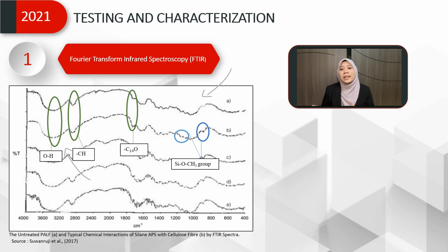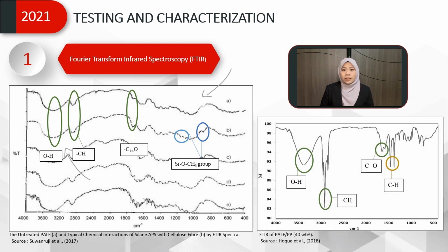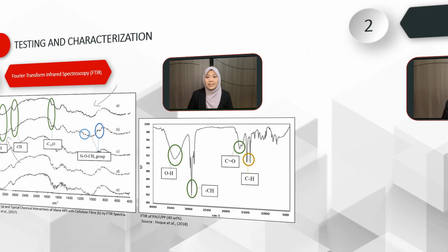hydroxyl group with silanes. The results reported in this article also show the appearance of OH, CH and C=O peaks. However, the peaks that appeared in this article are sharper. Additionally, a sharp peak for CH bonding is visible, which is generated by PP composites. This result indicates that the element bonding was changed when fiber loading was mixed with PP composites.